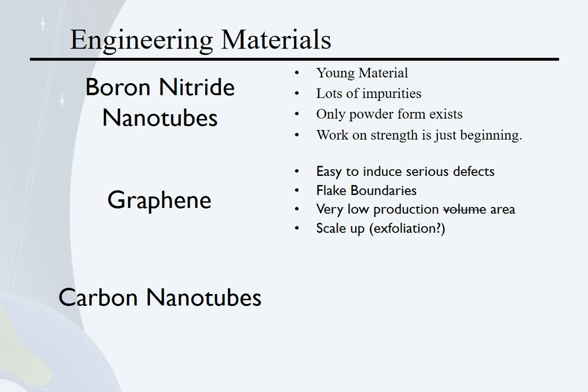And we've got graphene. So graphene, a little older material than boron nitride, but we've got some issues. It's very easy to induce serious defects, even in a carefully controlled synthesis, because of the way we make graphene. And because graphene just has that single layer and no way to stabilize that layer, each defect is potentially catastrophic, and it can only handle a very small amount of defects before its tensile strength or other properties drop off beyond the usable point. Far fewer defects in terms of a percentage of bonds than we would expect with nanotubes, whether they're boron nitride or carbon.